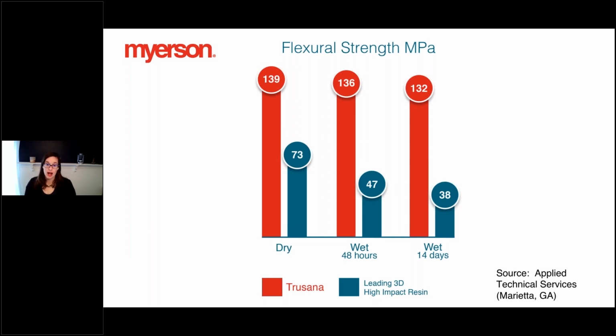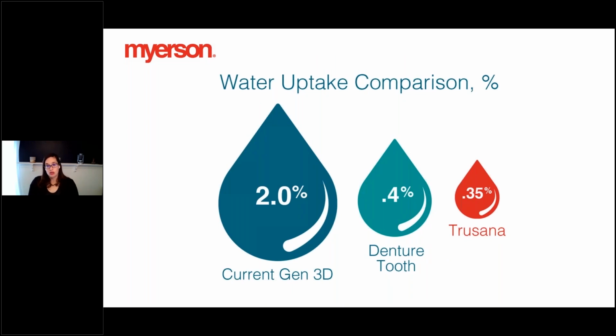So not only are the mechanical properties performing very well in class, but the water uptake is also quite remarkable, or the lack thereof, I should say. If you have a current generation of 3D printable resin, the water uptake tends to be around 2%. If you take a standard denture tooth, the water uptake tends to be around 0.4%. But with Trusana, the water uptake is 0.35%. And so that's part of the reason why we're getting such good mechanical properties, even after the 14 days of water exposure. Something we're really proud of with this material.